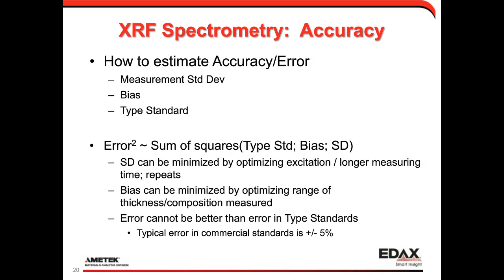Accuracy in these types of situations depends on a number of factors, and I just wanted to touch on those. So the accuracy can depend on the standard deviation, the precision of the measurement. If you're making a single measurement, your error has something to do with the standard deviation based on that single measurement. Any bias in the model, typically as they get thicker, the model may be a bit biased, and it helps to have a standard in that area to remove the bias. And you'll also have error in the type standard itself. Typical errors in type standards run around 5% or so. If you need something better, that's the kind of thing you have to specify.